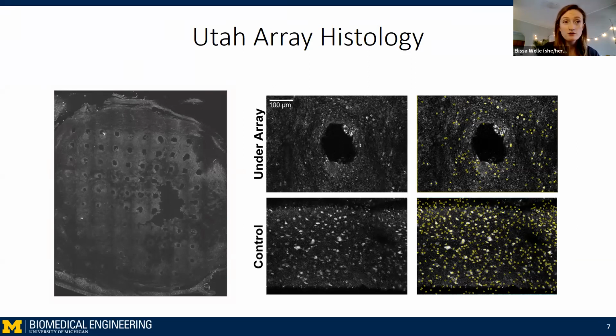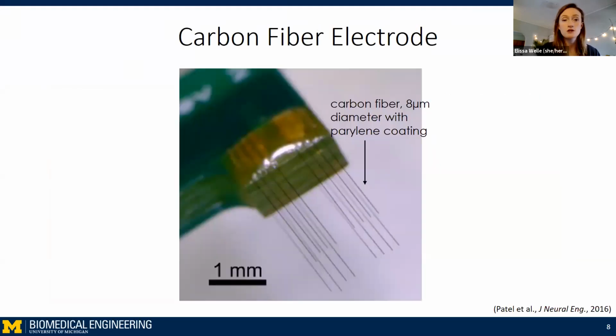People have come up with many alternative styles and types of electrodes to solve the scarring problem that we see with the Utah array. Our solution is small electrodes. In our lab, we work with carbon fiber electrodes specifically, each with an individual diameter of 8 microns, once coated with parylene insulation, with a 1 kilohertz impedance of less than 100 kiloohms when coated with PEDOT:PTS.